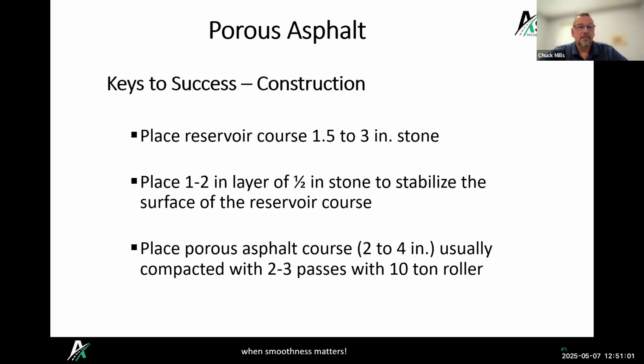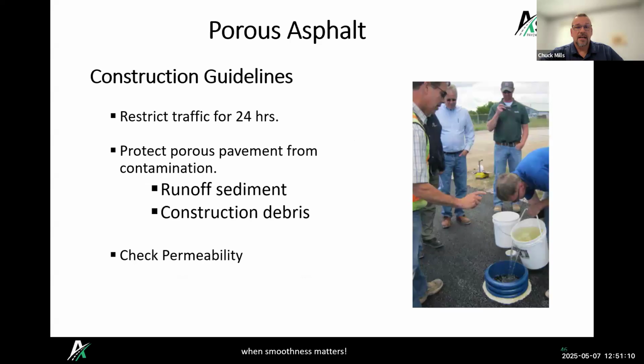So this is talking about construction. We want to cut down to the subgrade, prepare that, place the reservoir course, place our choker course, and then place the porous asphalt. After we do that, we want to restrict traffic to it for at least 24 hours. Again, protect that porous pavement from contamination and check the permeability. We want to make sure that the water is draining through it properly.